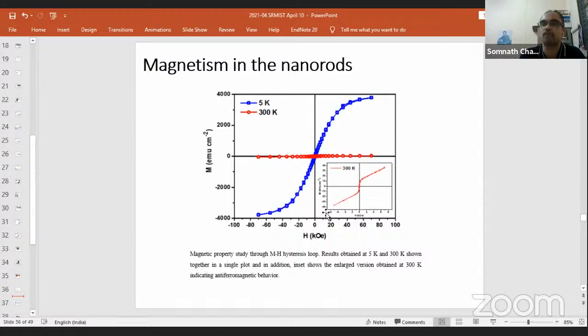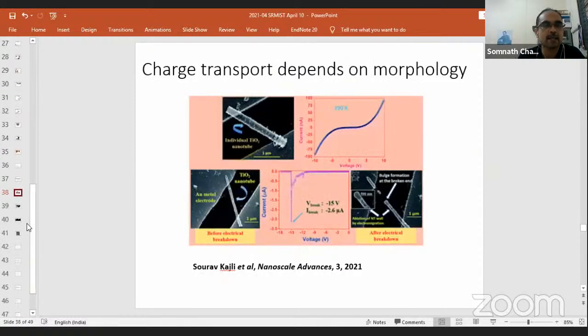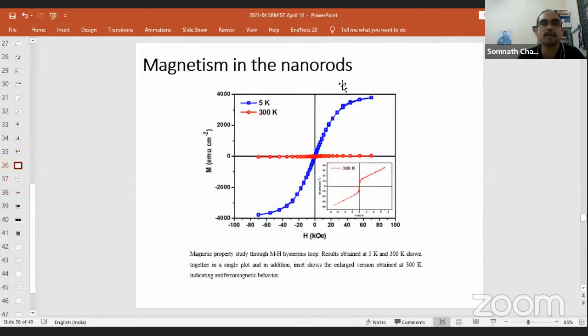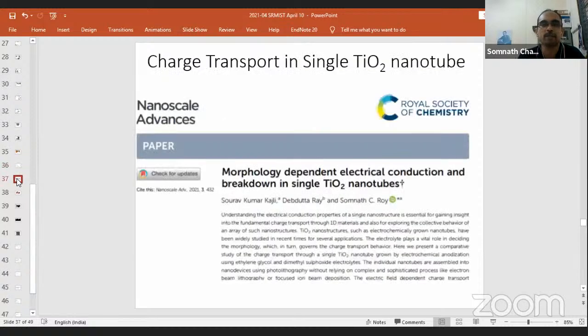But then this was the first report where, even if it's shorter, it was much longer than the previous report. Even if it is short, it was the first report of freestanding, vertically oriented TiO2 nanorod prepared without any template assistance. You will see a lot of work on template-assisted nanostructures. No template was used. Of course, you can say that we had a two-step process. So in a way, the first step might have worked as a template, but technically not.